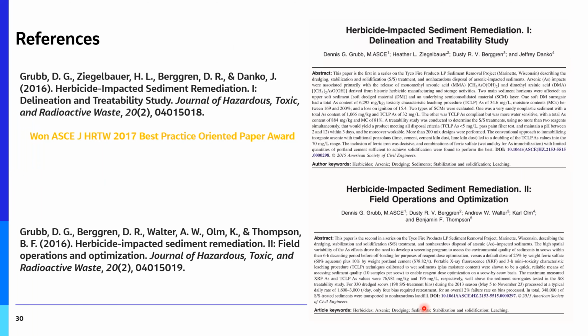So, you know, when you're in this territory, you don't have a lot of options, and we were actually very successful, thankfully. 3,300 screening samples from the scows, that's both initial and remixed. We had 76 scows that we reblended to knock the concentrations down, and four bin failures out of 198 bins, or just about 2%. And so with that, if you're interested in more details, this is published in ASCE.